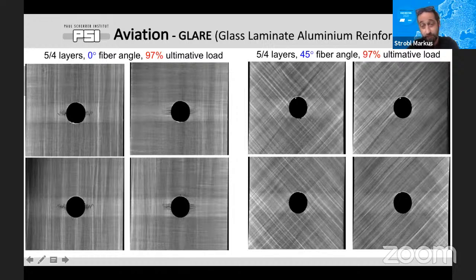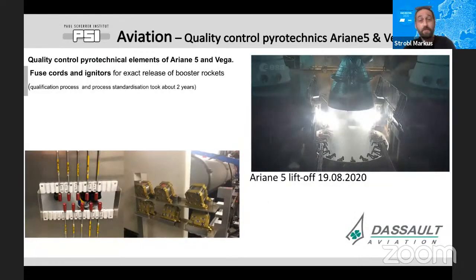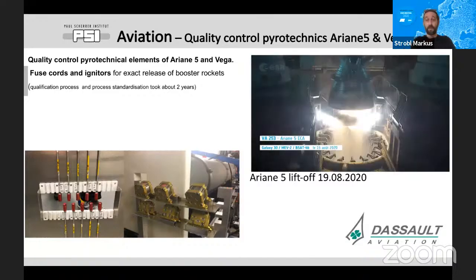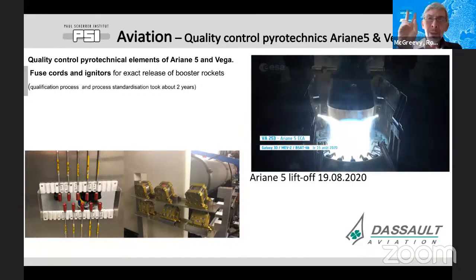And you can see here in these exemplified images the cracks under load appearing, and that the cracking under the same load is not appearing when you have diagonal orientation of the fibers to the load direction. So this is a simple insight, but it obviously helped this company. And now one of our biggest, yes, I will try to hurry.